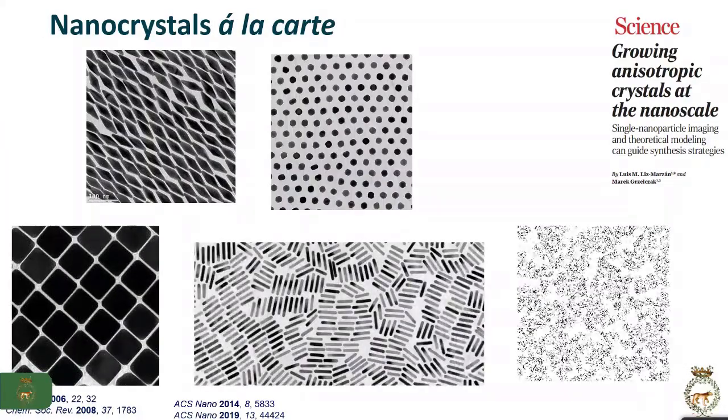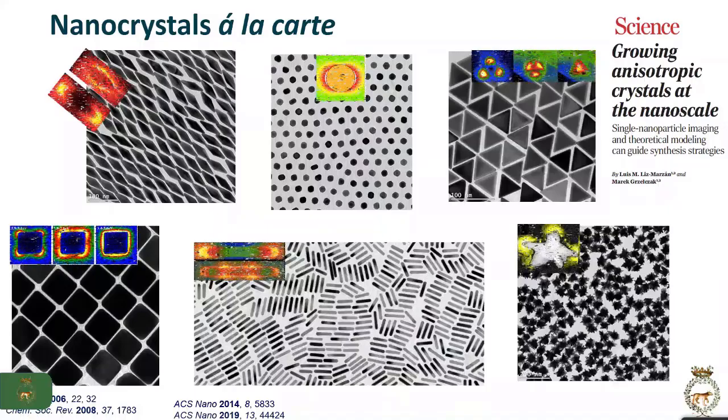So for many years, we and quite a few other groups in the world have been working on making gold and silver particles in different sizes, different morphologies, with very high quality. And we define quality as how similar the particles are to each other within a single sample. So what you see here are electron micrographs from droplets of a colloid that has been made by chemical colloidal science, where the particles look like this. They are all very similar to each other. They all have properties that are similar to each other. And this is what allows us to define what is the wavelength that we are going to apply.